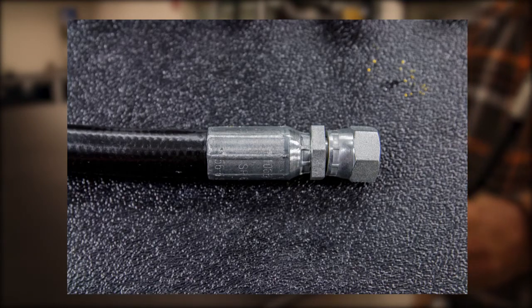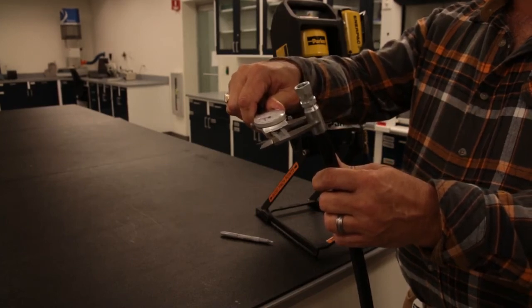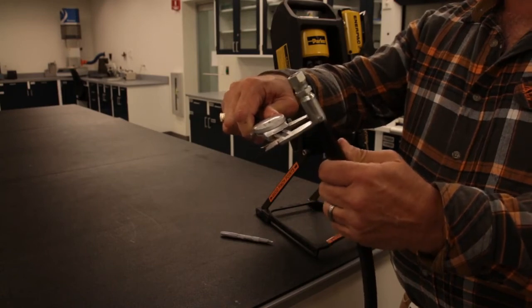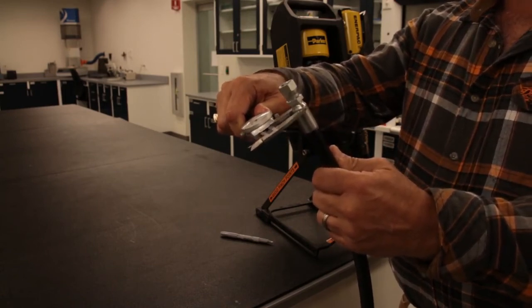Once you have properly crimped your fitting, you need to check the crimp diameter to ensure proper assembly. This is done by taking calipers and measuring the diameter of the crimp nine times. This would include three checks at the top, middle, and bottom of the fitting shell.